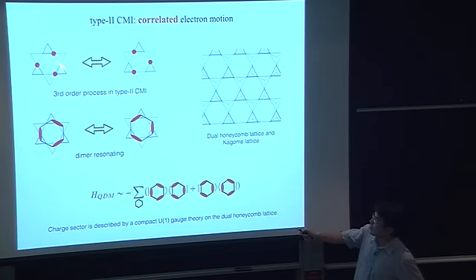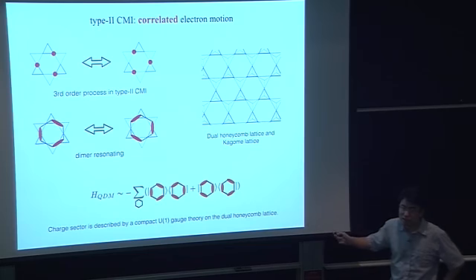This can be mapped into a dimer resonance. If you map each occupied electron site to a colored link, a dimer link connected in the center of 2 nearby triangles, then this electron configuration maps to this dimer configuration, and this electron configuration maps to this dimer configuration. So this third order process is called a dimer resonating process. The correlated electron motion in the type 2 cluster Mott insulator is mapped to dimer resonance on a dual honeycomb lattice. If we connect the